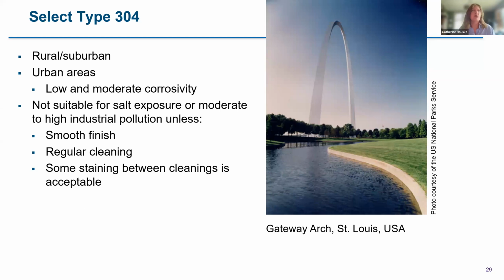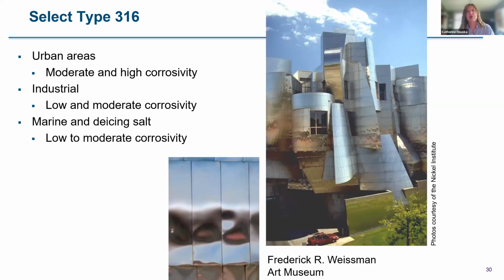Type 304 is great for rural and suburban areas with low pollution levels and where there's not much salt exposure. The Gateway Arch has type 304, it's structural on the exterior. It is in a park setting. There is some corrosion on it, but not much. It doesn't get direct salt exposure from de-icing salt other than right at the base, and they've been changing what they're doing there. Most of the discoloration on it is actually from industrial pollutants when St. Louis was a much more industrial city. But if you have a smooth finish and you have regular cleaning, sometimes you can get away with 304. But both of those have to occur.